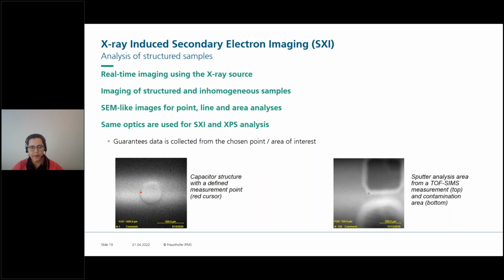And on the right-hand side, you see a sample which has an inhomogeneous surface. At the top, you see a sputter analysis area from TOF-SIMS, and at the bottom, you see a contamination area. So this can help you find your way around unwanted features.